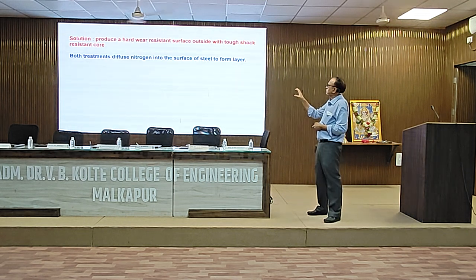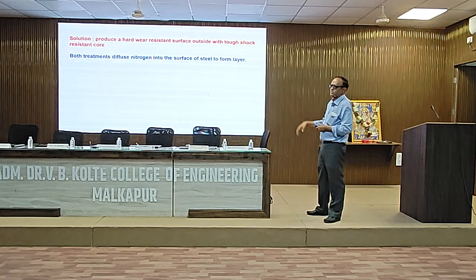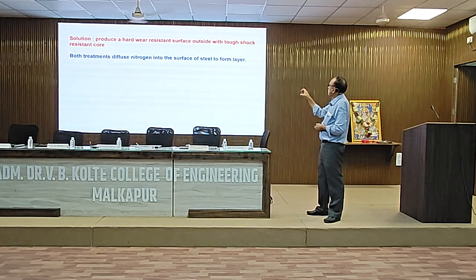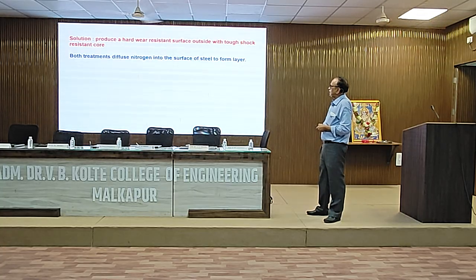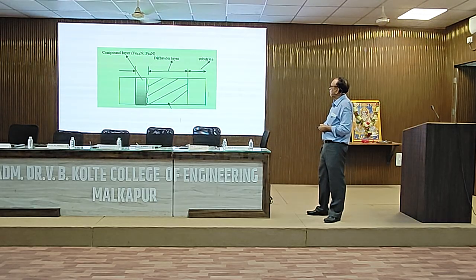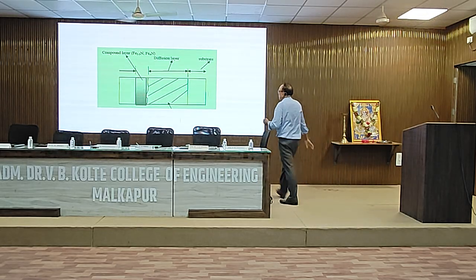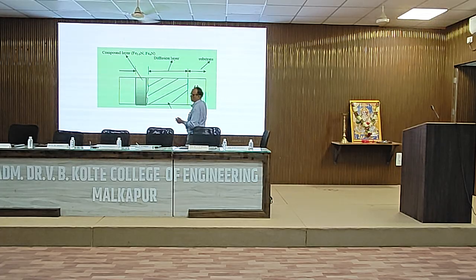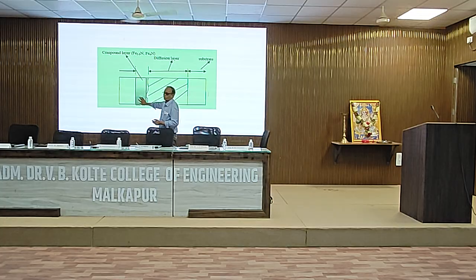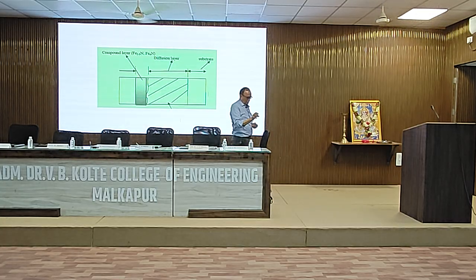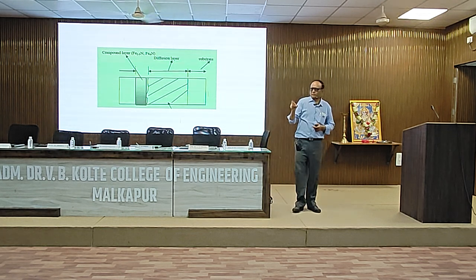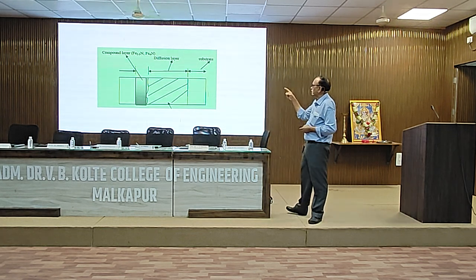You produce a hard, wear resistant surface outside, with a tough, shock resistant core. And this treatment involves diffusion of nitrogen into the surface of steel to form the layer. So this is basically the scenario. You have the steel component, this is your tool component, this is a diffusion layer in which the nitrogen is diffused, and this is the layer in which your compound layer, that is nitride phases, are formed. And again, these nitride layers form as a mixture of two phases: epsilon phase, that is Fe2-3N, and gamma phase, that is Fe4N.